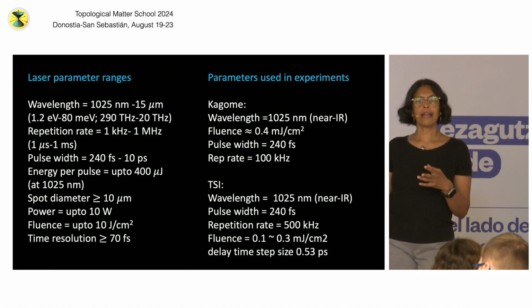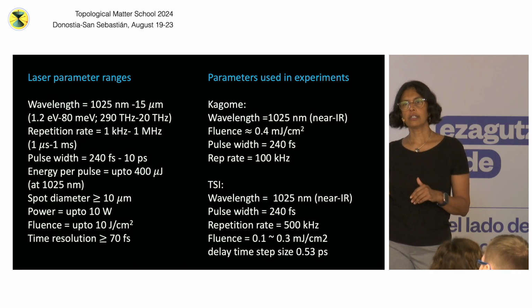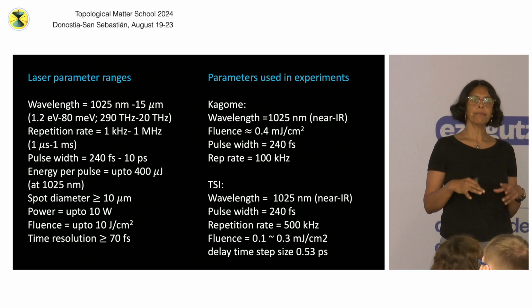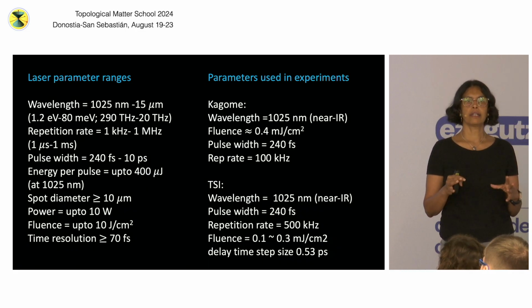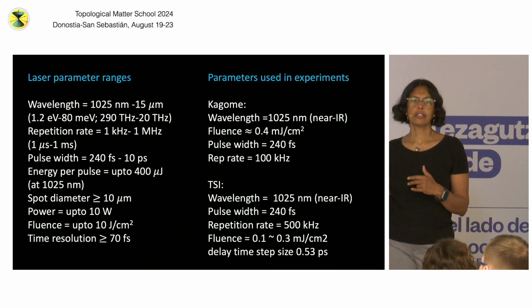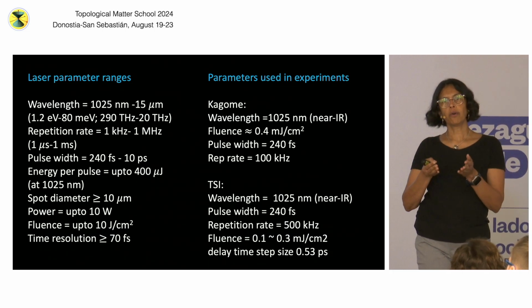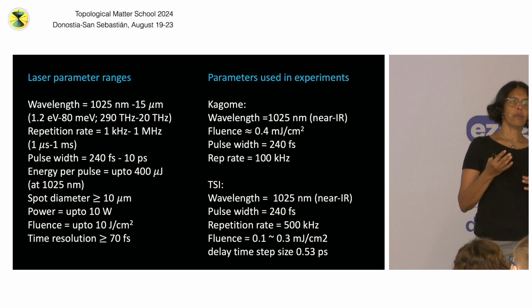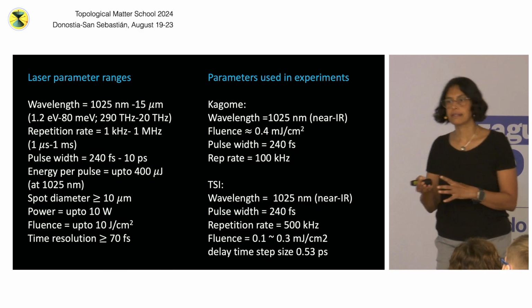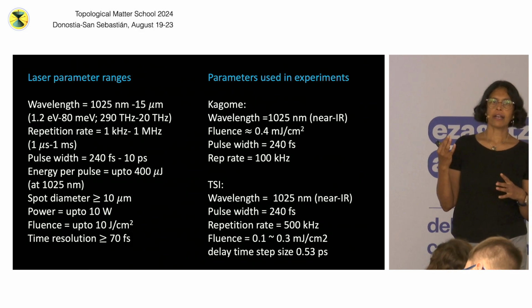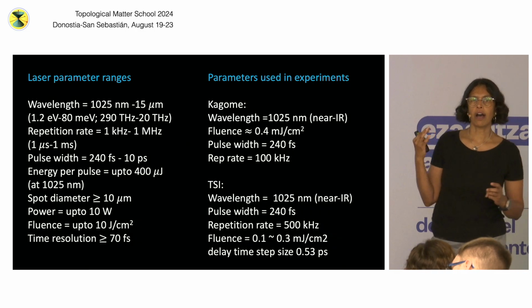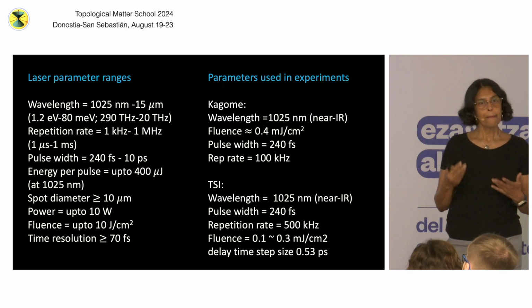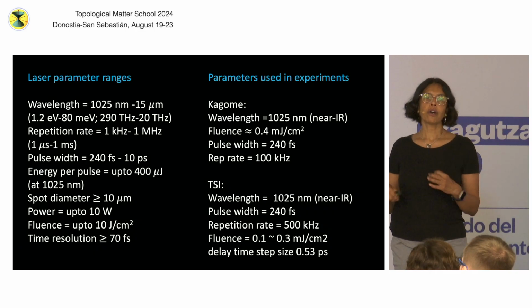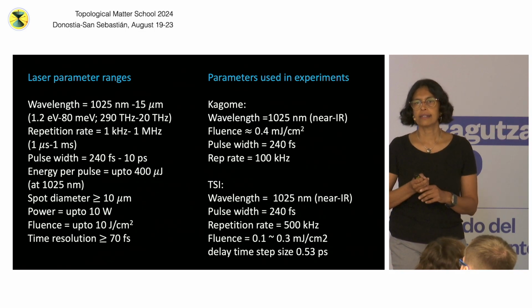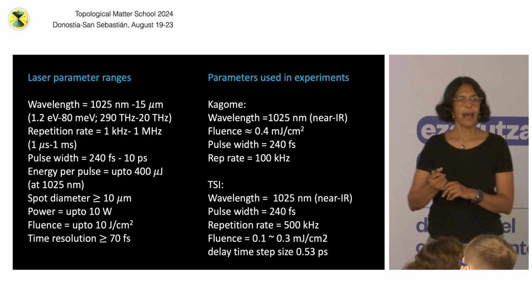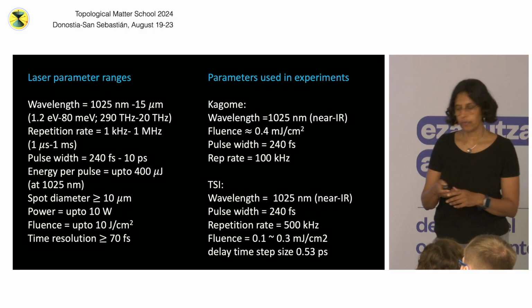But in this class of materials, it actually becomes an insulator below the CDW transition. And due to that, there are very few quasiparticles for screening, so the Coulomb interactions are not screened. And because of having strong Coulomb interactions, you can go from having a massless phase mode to a massive phase mode. And this massive phase mode, the way the particles acquire mass, is very similar to the Higgs mechanism. It was predicted a long time ago, but never measured, actually. And so last year, one of my colleagues, Fahad Mahmood, saw evidence for the existence of this massive phason in this compound. And I'll show you what we see with our technique. This phason has a frequency of terahertz, and I'll show you what we measure and how we can get additional information through what we're doing.